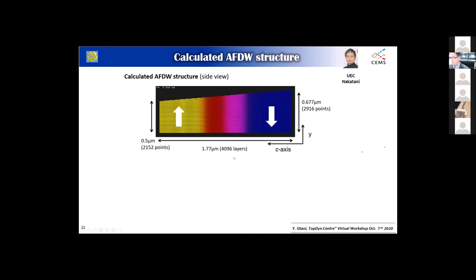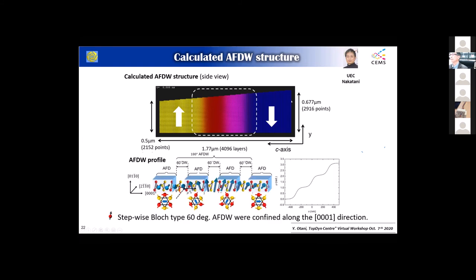We are interested in the domain wall profile. This is a wedge-shaped sample because, as I said, Bloch walls and Néel walls have more or less similar energy scales. In order to make the Bloch wall more stable, we apply a slope shape so that we can have a straight Bloch-wall-type structure. The calculation showed exactly what we expected: the angular profile goes from zero to 2π with hexagonal six-fold symmetry, giving 60-degree domain walls — cluster octopole domain walls sandwiching different antiferromagnetic domains, which are cluster octopole domains. Plotting the angular events shows this kind of stepwise change.